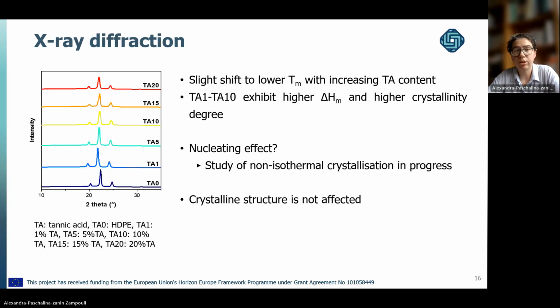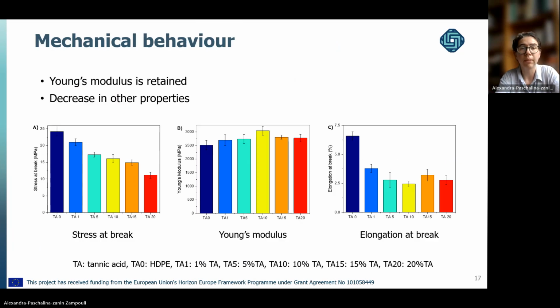The crystalline structure of HDPE is not affected by the presence of tannic acid. When it comes to the mechanical behavior, Young's modulus is a bit increased or retained with the incorporation of tannic acid. But on the other hand, the stress at break and elongation at break steadily decrease proportionally to tannic acid.